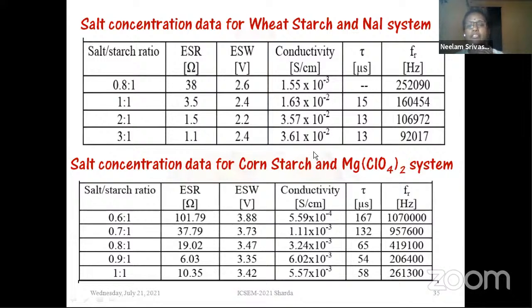The conductivity is also very high, 10 to the minus 2. For magnesium, it is of the order of 10 to the minus 3. And if we increase the salt concentration, the students have studied till 1:1. We are trying to study higher values of salt concentration, and hope that it will increase further.